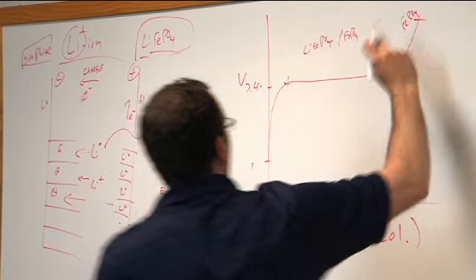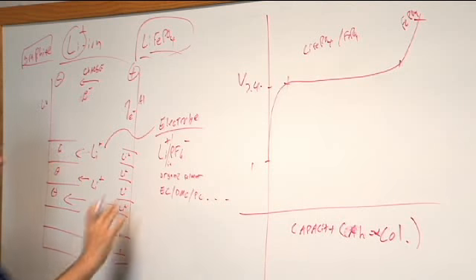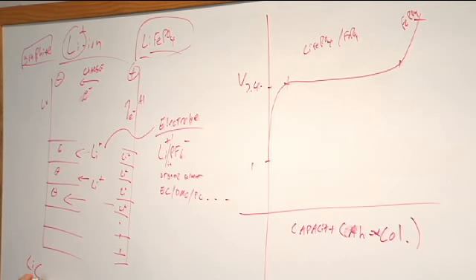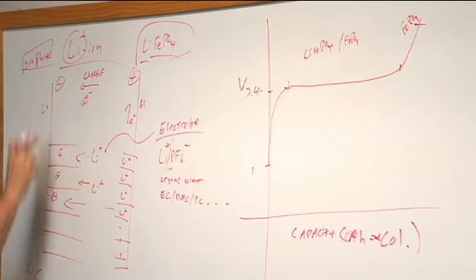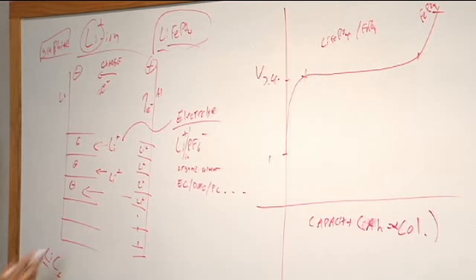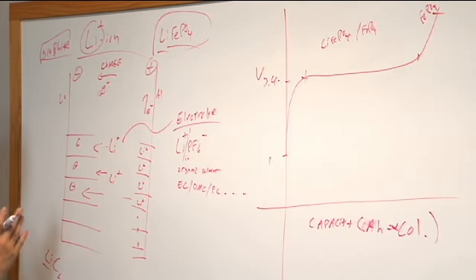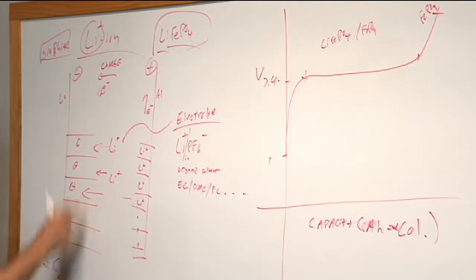And when we're up here, all the lithium, in principle, is gone from our lithium iron phosphate, and it's all over here. So we've got iron phosphate, and then we've got LiC6. For every 6 carbon atoms that we have in our graphite, there's 1 lithium sort of stuck inside. And this is why it's called a lithium-ion battery. In fact, the only lithium that exists in this system free are the ions that are in between. At the cathode and the anode, we are actually intercalating. The word is intercalation. We're intercalating lithium into the graphite during charge, and we're deintercalating it from the graphite and reintercalating it into the cathode during discharge.